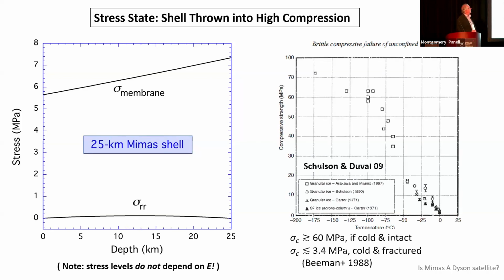Now, you can compare it to the unconfined compressive strength of solid pure laboratory ice. And if the ice is cold, as the surface of Mimas is, then it will in fact support that kind of stress. But if the ice is cracked, if the ice is fractured, the shell will not be able to support that stress. The unconfined compressive strength of cracked ice is no more than a few megapascals and probably lower.